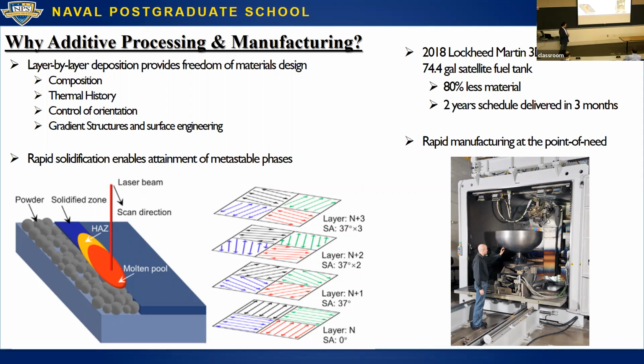Industry likes it because you can design something on your computer and you can go prototype it right away. But as a material scientist, I really like this technique because it allows us to essentially synthesize materials layer by layer. And we're talking about pretty fine layers, micron size. And there's definitely some challenges to it. Each layer is almost like a single welding process. I'll talk about some of the challenges in the next slide, but to give you an idea, you can change things in a single layer by how you're rastering the beam, the direction that you're rastering the beam, the different parameters associated with the beam, such as the speed, the power, the energy density.